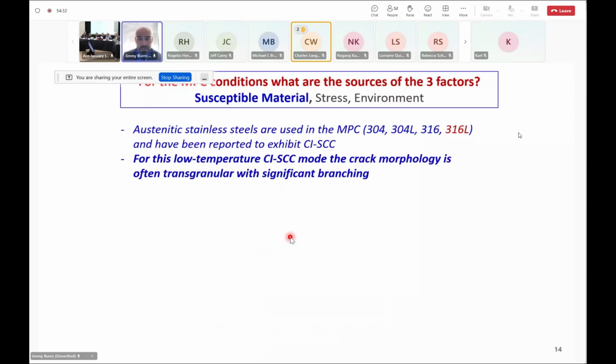So for this low temperature cracking mode, and we consider this low to intermediate temperatures, the temperatures that we're talking about here, as compared to some of the other work that maybe you would find in the literature at higher temperatures relevant to actual in-reactor sites. The crack morphology is often what we call transgranular, and it can show a significant amount of branching. Jerry showed that in his slides earlier, where you had a significant amount of branching. It wasn't a single crack front running forward, and that's somewhat typical of this damage mode in this material system.